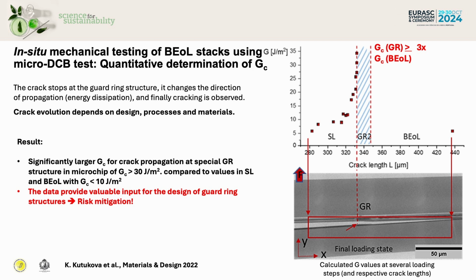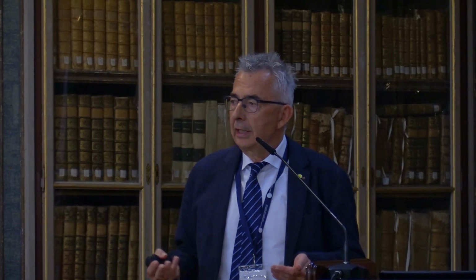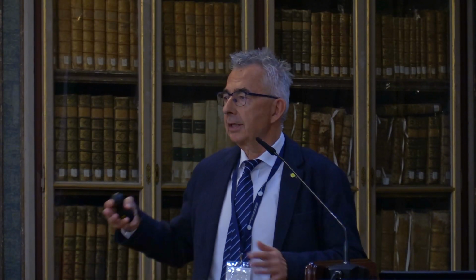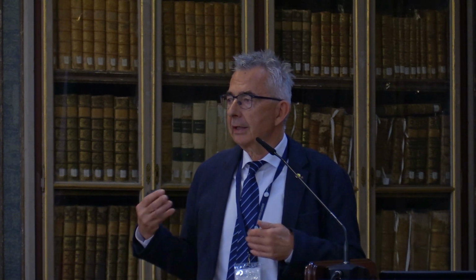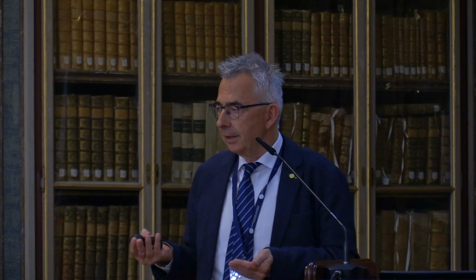And interestingly, you see here on the right-hand side on top, the energy release rate. You see it in the scribe line, on the left-hand side, then you see the guarding structure, and then you see the active area of the chip. And you see the guarding works. The energy release rate, it's practically fracture toughness, is increased by more than a factor of 3.